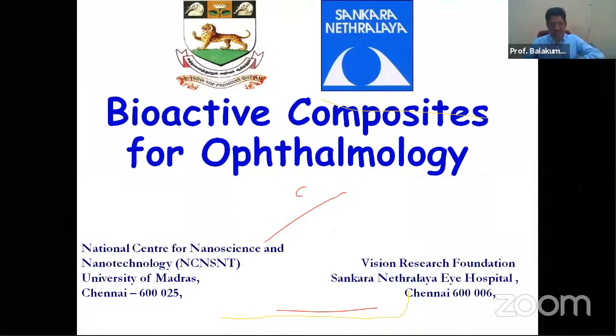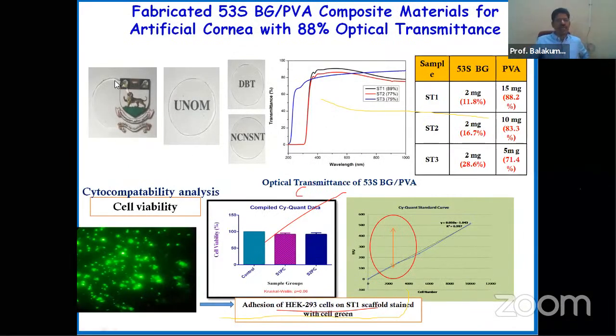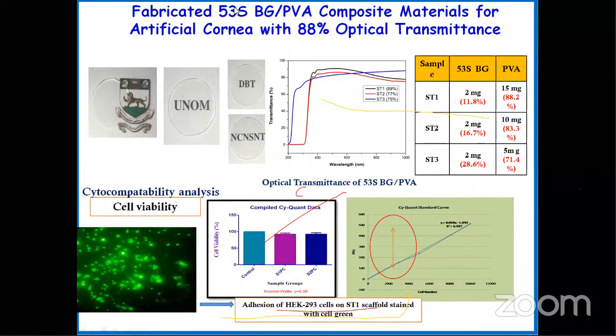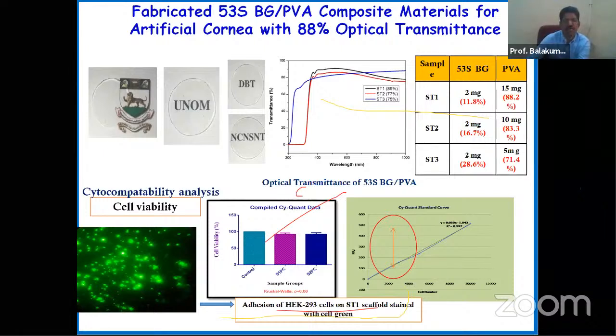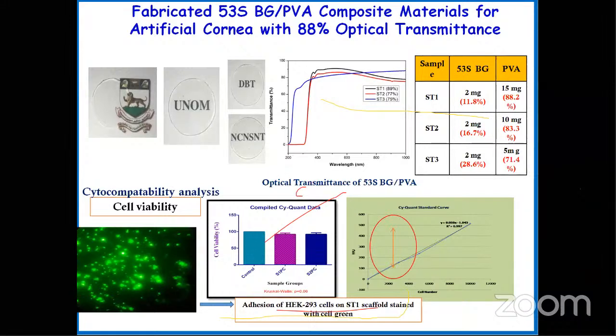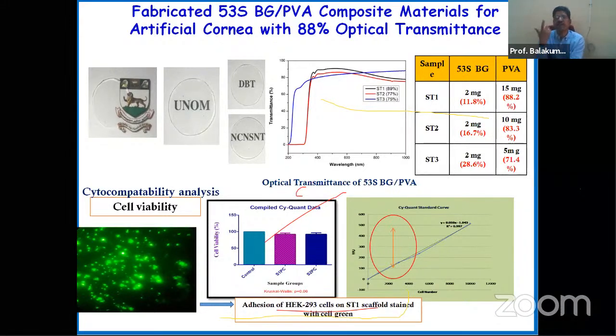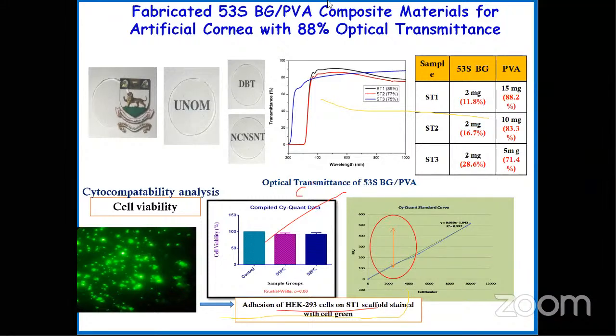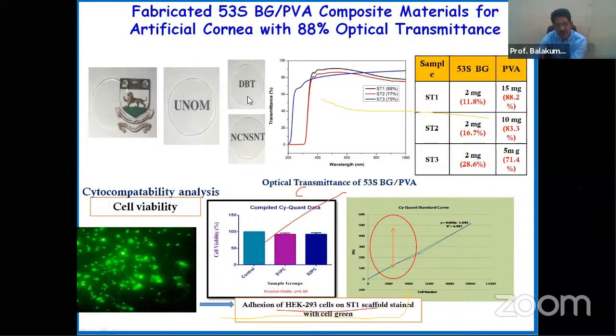So another area for the next 5 minutes I'm going to discuss is a bioactive composite for ophthalmology. The same material, if you use the right composition, can be used for corneal application. This is a scaffold we have prepared with the polymer bioglass with 53% of silica and the PVA composite for artificial corneal application. First, this material should not degrade, and second, the transparency should be equal to the natural cornea. So we have fabricated this material, and with the help of a small mold we made a corneal membrane with different thicknesses. This is a joint project with the Sankara Nethralaya Hospital, and we achieved the transmittance up